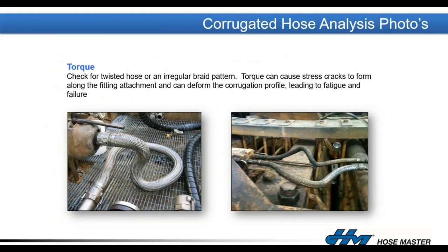These are just some pictures of typical assemblies out in the field that you want to avoid. The hose on the left is installed with the end fittings 90 degrees away from each other, and pretty much any way the customer tries to move that hose, they're going to twist that assembly. So avoid those applications or install some sort of swivel fitting on that hose to prevent it from being twisted. You can see the hoses on the right were actually installed in a twisted position, and they're probably too long for that application. Those hoses need to be replaced.